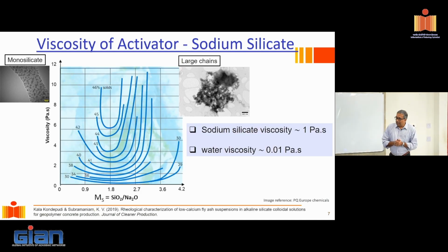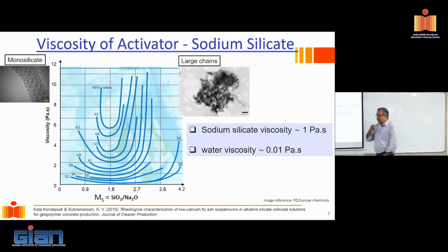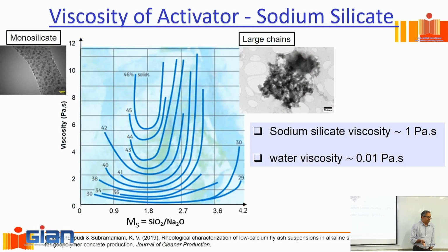Now, there's also something very interesting about silica. When you add silica into water, its state and shape depends upon two things. And one of the primary variables that controls the shape and the state it's present in is the MS. This is the silica to sodium ratio in the solution. Where do I get this from? My activating solution is a combination of sodium hydroxide and sodium silicate. Sodium silicate brings in the silica, and the sodium hydroxide and the sodium silicate bring in the Na2O. So in the activating solution, I get this silica to sodium ratio. We call this the molar ratio or the silica ratio. Different terms are used, but in short form, we typically just call it MS.